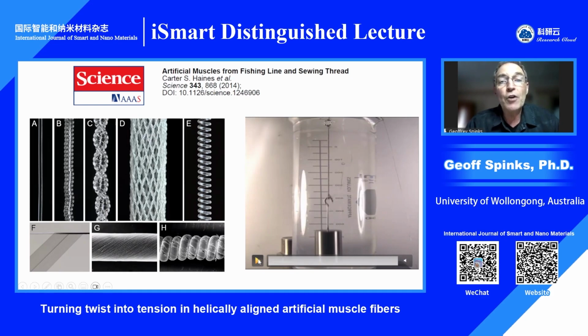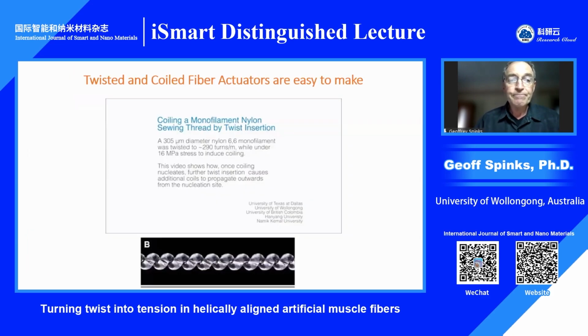Reasonably large strokes, in this case about 10%, but it can be a lot higher. And it can be very fast, depending on how quickly you can get the stimulus in and out. And those two things combine to produce quite high power. In fact, as we'll see, power per weight, which approaches that of the turbine engines of 1,000 watts per kilogram.